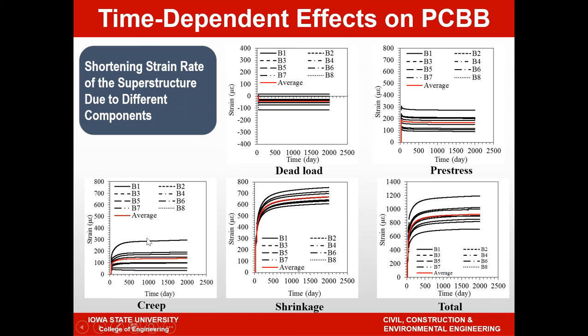Then you have creep strain as well as the shrinkage strains. As I said, the shrinkage strains are typically much higher. So you can see in this case we have shrinkage strains of about 575 all the way to about 775 microstrain. In the bottom right corner you see the total strain. So this basically gives you a feel for the shortening strain of the superstructure. And you could see that from B1 through B8, we have a shortening strain of anywhere from 650 all the way to close to 1200 microstrain.